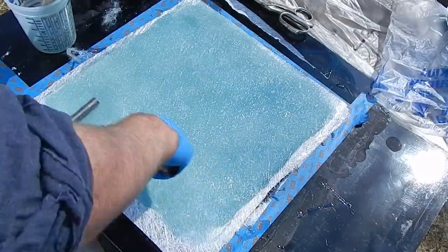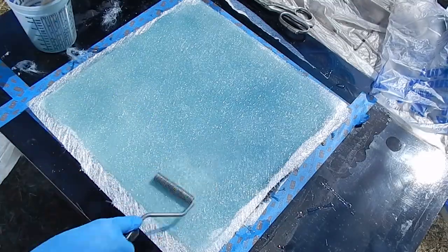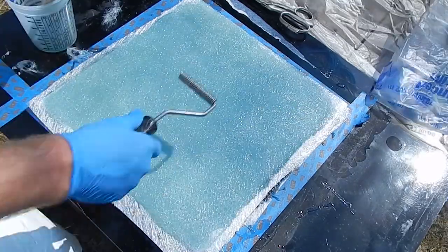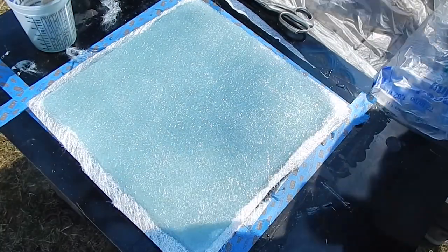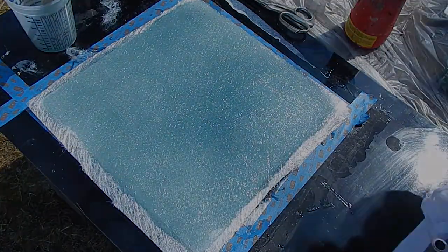This is going to have to cure itself at a much lower temperature. This is probably outside the reasonable window for polyester resin at 55F, but it's in the sun and it will work. It's really important not to do this too cold.